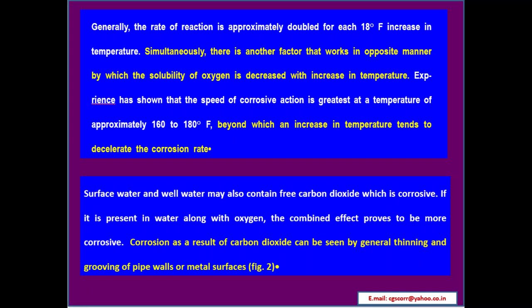Simultaneously, there is another factor that works in the opposite manner, by which the solubility of oxygen is decreased with an increase in temperature. Experience has shown that the speed of corrosive action is greatest at a temperature of approximately 160 to 180 degrees Fahrenheit, beyond which an increase in temperature tends to decelerate the corrosion rate.